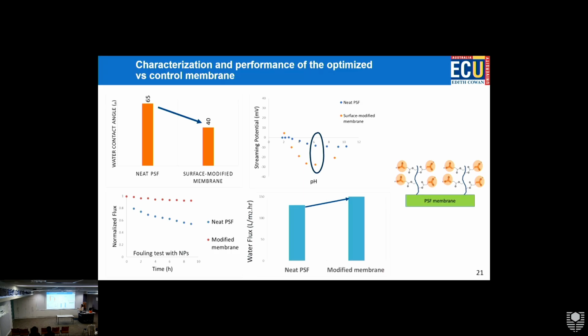This is streaming potential data from an Anton Paar streaming potential analyzer. Over a wide range of pH, we do surface charge analysis on the surface of the membranes. As I mentioned, surface charge plays an important part in reducing fouling. As you can see, the modified membranes have more negative surface charge, which is, again, advantageous for repelling negatively charged microplastics. And in this case, you see the fouling data: the neat membrane, after a while, starts to decrease in terms of water production, but the modified membrane stays almost stable, so it's advantageous to its durability and long-term operation. And with the water flux, again, the modified membrane performed much better. Not much better, but better, basically.